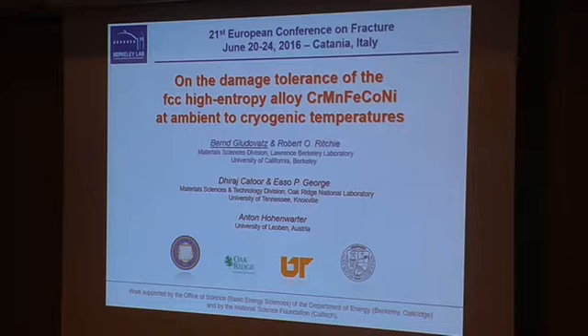When we started with our fracture toughness measurements, we decided to make compact tension specimens, nicely sized, rather on the larger size for what we are normally doing. They had a W of 18 millimeter and a sample thickness of about 9 millimeter. All the samples were machined by EDM. The surfaces were subsequently polished with silicon carbide paper. Then we pre-cracked the samples in tension at an R of 0.1 and side-grooved the samples in order to increase the constraint at the crack tip, and did our testing again at room temperature.